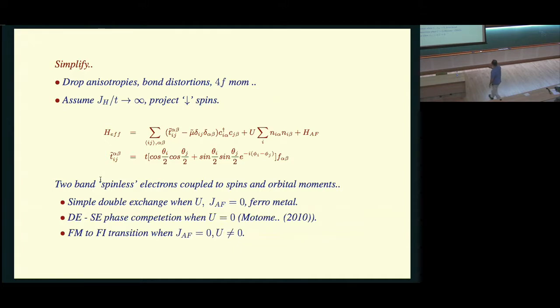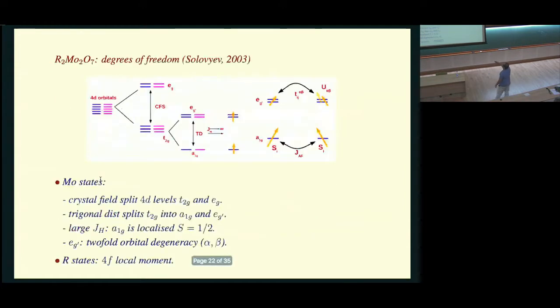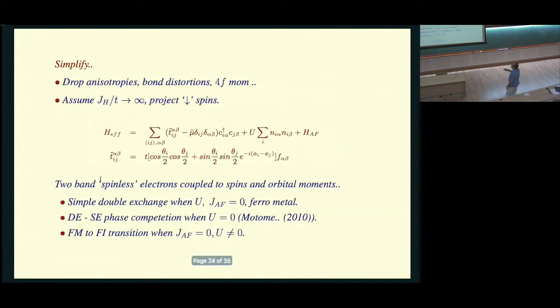Why is it spin-dependent? Because to move from this site to this site, you need to bother about what the core spins are doing. Sort of again, a reflection of what one saw in the manganites. Large Hund's coupling forces this electron spin to be parallel to this electron spin. These are antiferro coupled. So the underlying magnetic state is going to dictate the hopping of these electrons. As a result, the hopping takes on a complicated form here, depending on the angles at neighboring sites, the orbital Hubbard interaction, and an antiferro coupling.